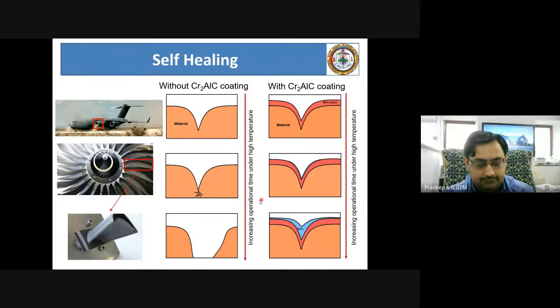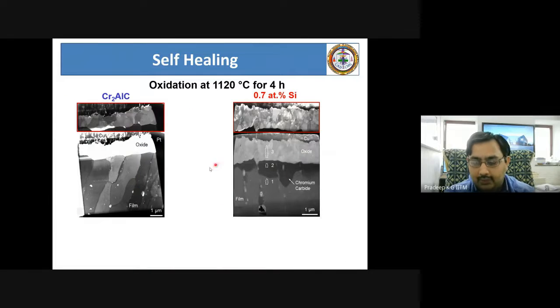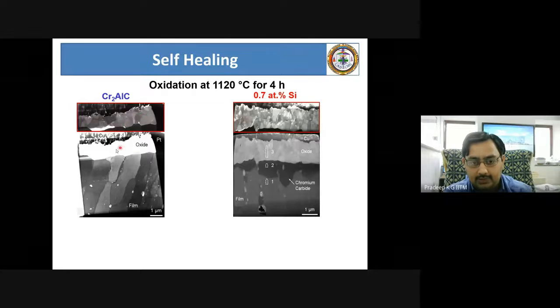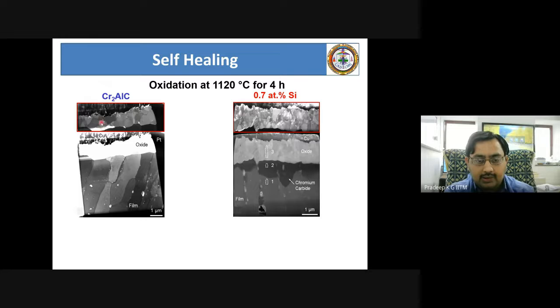Now an example of how this has happened is this one. So we make a thin film coating of the MAX phase chromium aluminum carbide, anneal it at 1120 degrees for 4 hours, and see what kind of oxide is forming on the surface. That means the image you see on the top is the same oxide. Because of better contrast, I put it here. You see these nanoscale grains of aluminum oxide formed on the surface, and when you add the same MAX phase with 0.7% of silicon doping, we are interested in accelerating the oxide formation in situ at this temperature in the atmosphere, so that we can get a much thicker layer of this oxide,